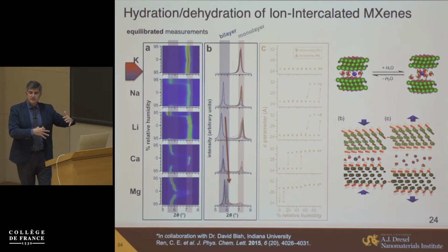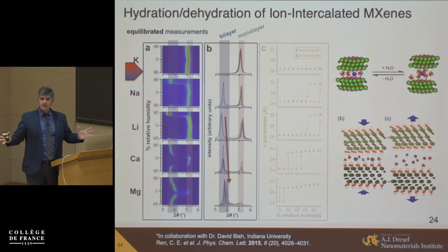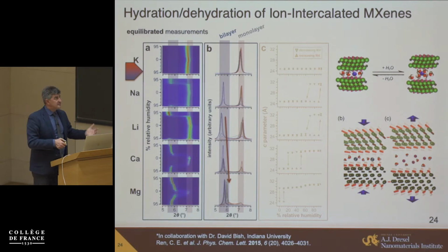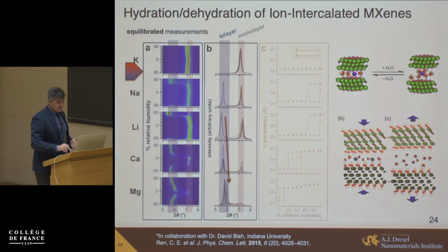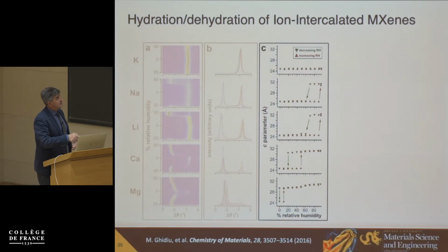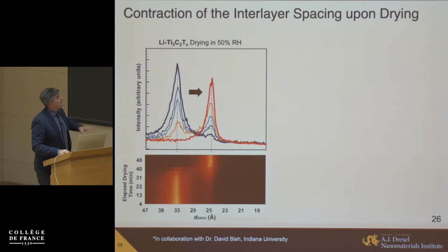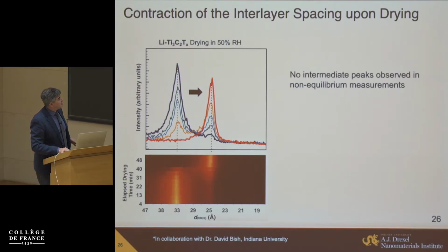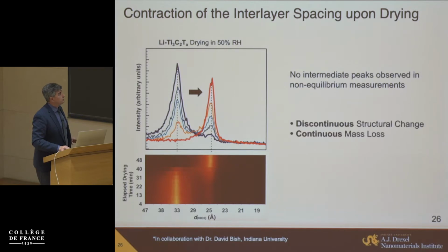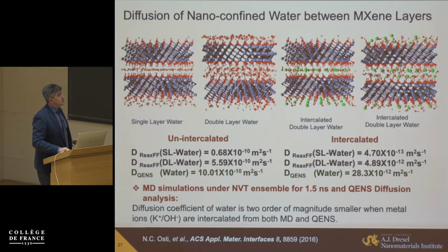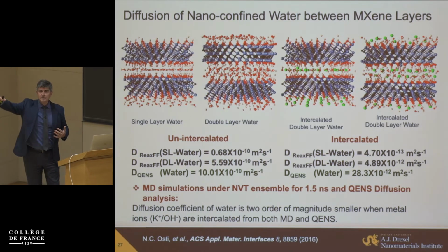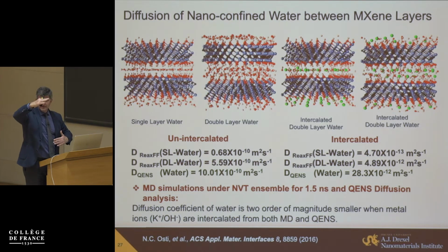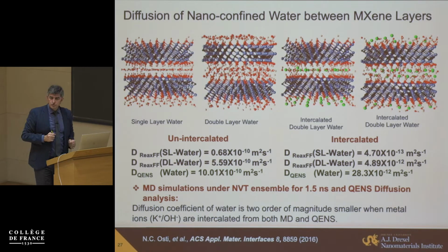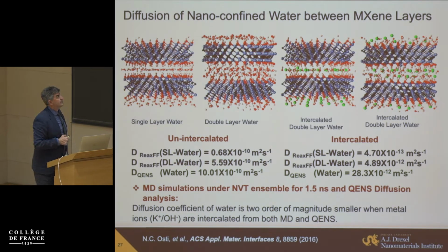So we get a special case, solvation not in a bulk, but solvation in confinement. We have a different number of molecules solvating ions here. And we get this type of jump-wise changes if you look at lattice parameter. I'm going to skip it further here, but we showed it on many different ions, this discontinuous change, even if you have continuous mass change. You get ions, but at a certain point you make a jump in the behavior, and I will show you how important it is a little bit later here.